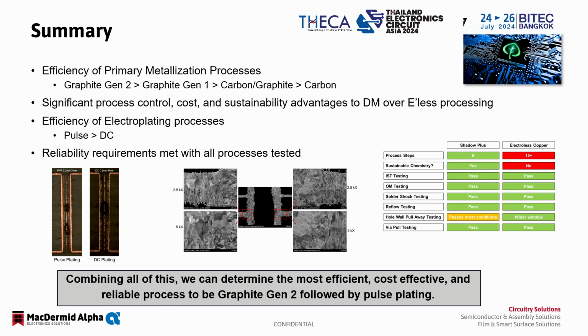And then when we look at the efficiency of our plating process, we could see a significant benefit using pulse technology versus DC. So when you combine those, it's clear that the pulse process with graphite Gen 2 is going to be the best performing and best way to go. And from a reliability standpoint, there's no difference. So you might as well go with what's going to give us a better sustainability and cost advantage.